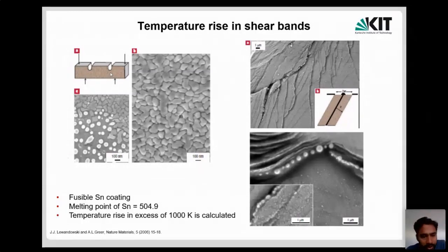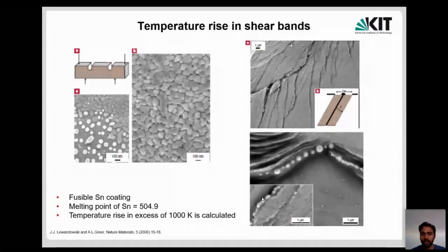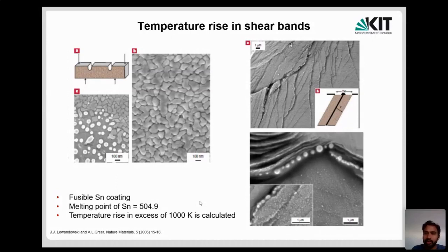And as you all know, the melting point of tin is 504 Kelvin. So when the melting point is so low, if you generate a band, and if the band is catastrophic like what I showed before, then there must be some temperature rise, and that temperature rise would cause the tin to melt. And that would give you, if you see this bottom picture here, this kind of tiny droplets. Okay, the tin melted and formed these droplets, and that indicated to them that the band has a higher temperature. So this is a very nice experiment to understand that shear bands show excessive rise in temperatures.